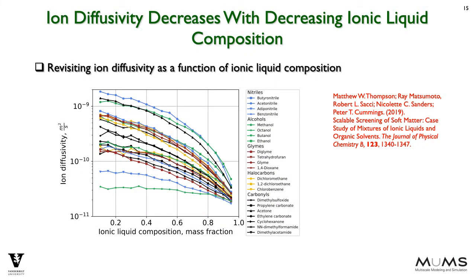So using MOSDEF, we performed molecular dynamics-based screening calculations using 22 different organic solvents, listed to the right of the figure in this slide, at 18 different compositions of BMIM TFSI, for a total of 396 distinct systems. In this figure, the BMIM diffusivity is plotted as a function of ionic liquid mass fraction in the 22 solvents, each identified by color coding. Note that the plot is log-linear, with the diffusivity in some solvents, for example acetonitrile, differing by two orders of magnitude over the concentration range from dilute at the left of the graph to concentrated at the right. All of the curves come together at one point at mass fraction one, since this corresponds to neat BMIM TFSI.